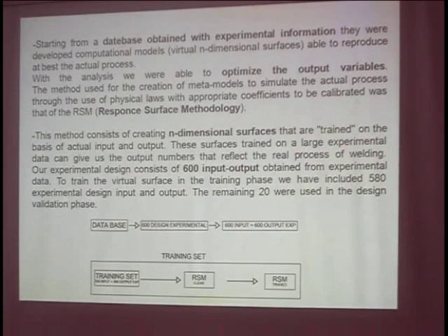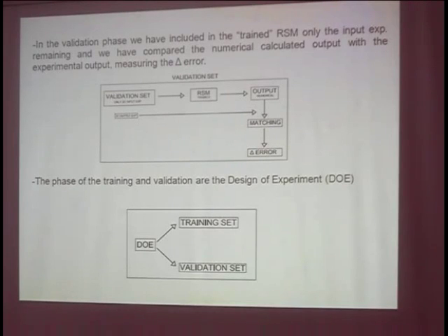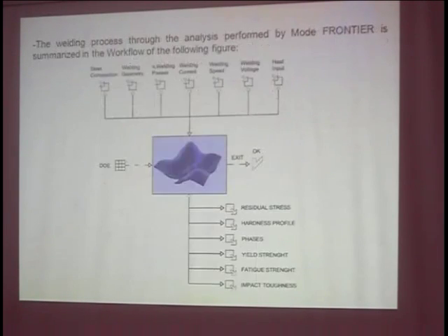580 were employed to train the system, and the remaining 20 were employed as validation for the final properties of the material. In this way, it is possible to train the response surface we obtain through the analysis of the input and output experimental data and correlate to the remaining 20 properties to a delta error, which gives us the goodness or not of the analysis we perform. This is the workflow which is worked by modeFRONTIER.